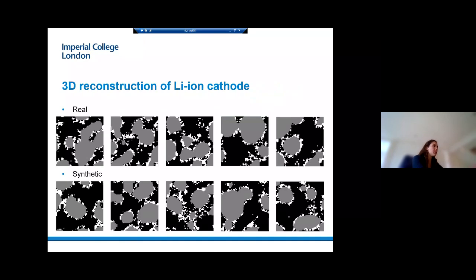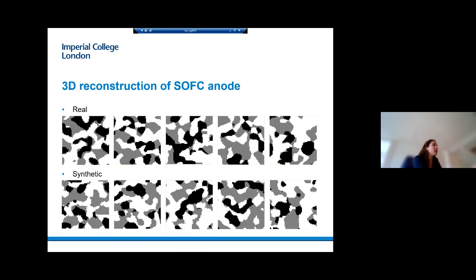Once we had implemented our learning process, we can obtain some samples of the synthetic images. And as you can see, this is a comparison of what the real microstructure looks like and what the generated microstructure looks like. So visually, you can see that there is no difference between the real and synthetic images. And if we see the same for the SOFC anode, we can see again that basically there's no visual difference between either of them.